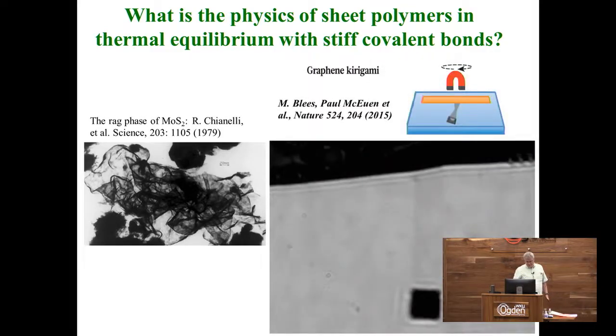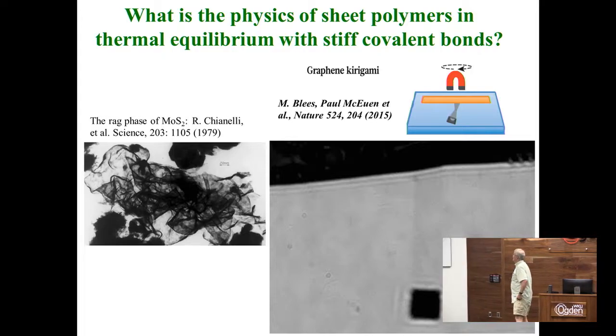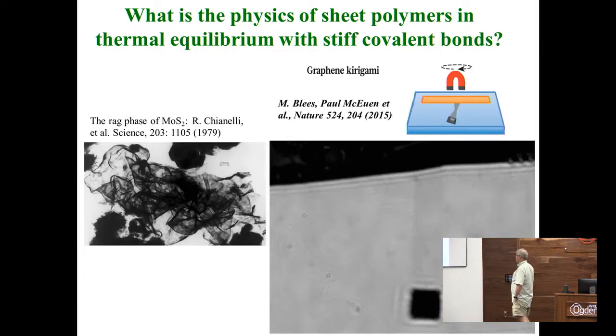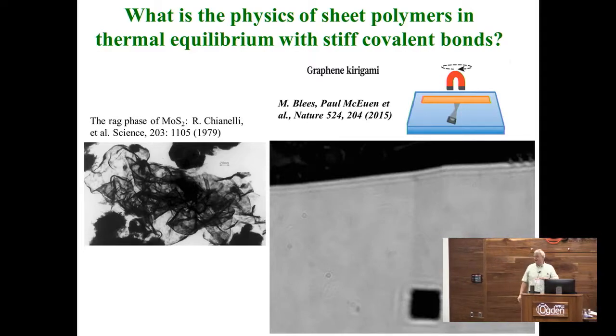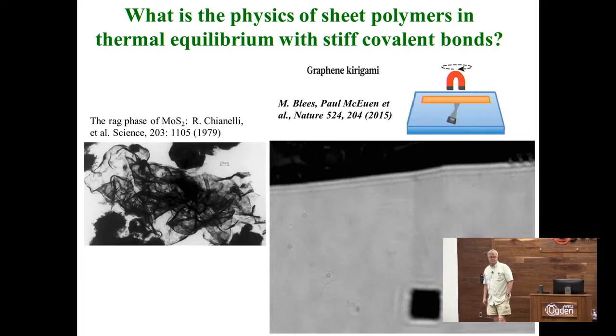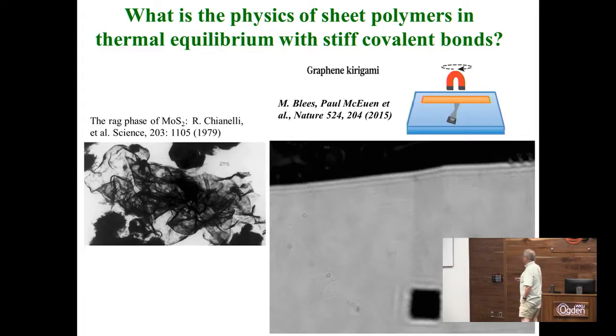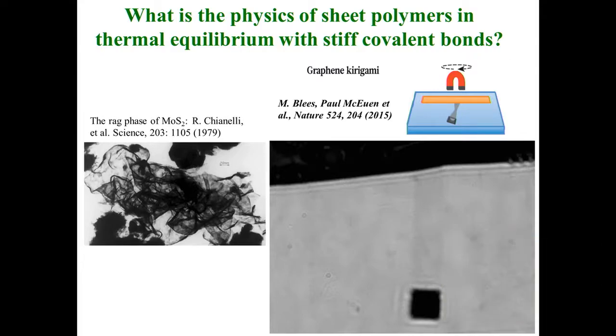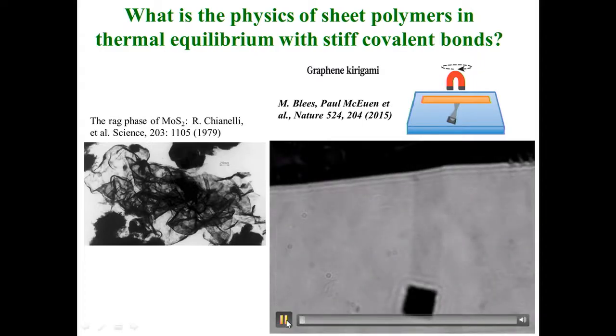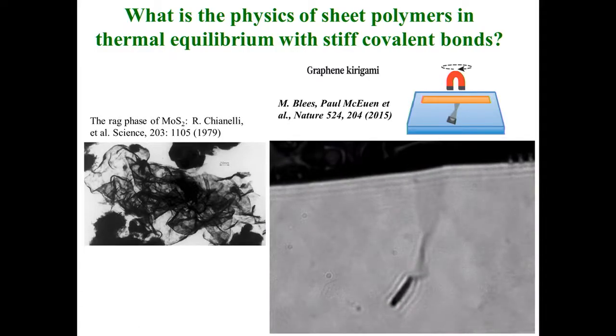What drew me back into this field a couple of years ago were some remarkable experiments, not on molybdenum disulfide, which is a common lubricant, but on graphene. Graphene, some of you may have heard, is an atomically thin collection of carbon atoms arranged in a honeycomb lattice. And what these experimenters in Paul McEuen's group succeeded in doing was freely suspending it, that is, without any support, basically embedded in a water bath, attached to the top but with a magnetic pad at the bottom. And they were able to actually get this atomically thin ribbon separated from the substrate and free to float around and be subject to Brownian motion and thermal fluctuations at room temperature. This had never been done before.